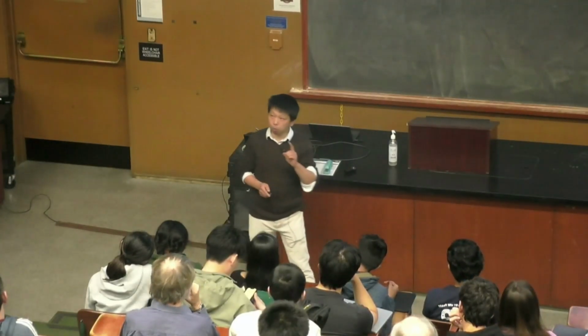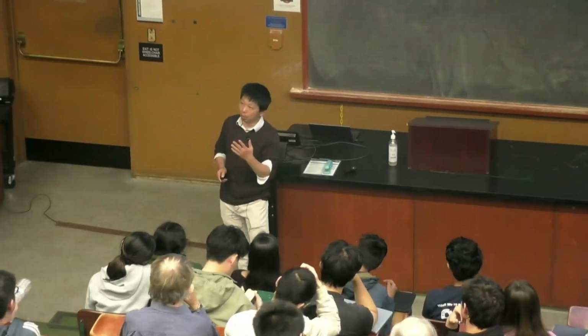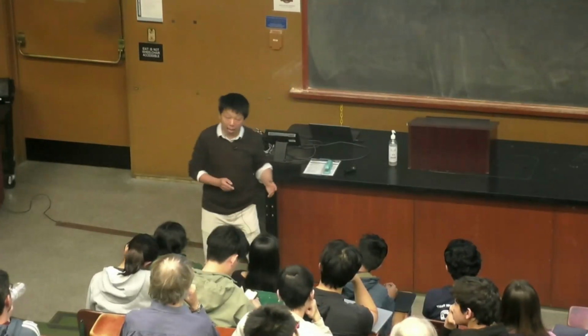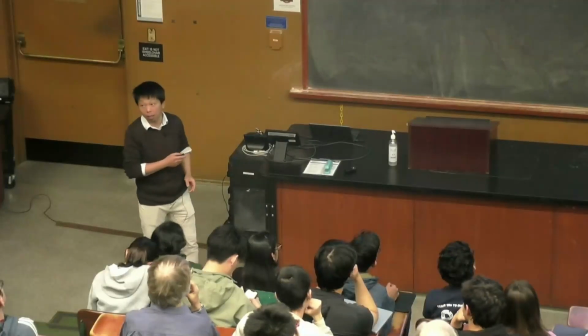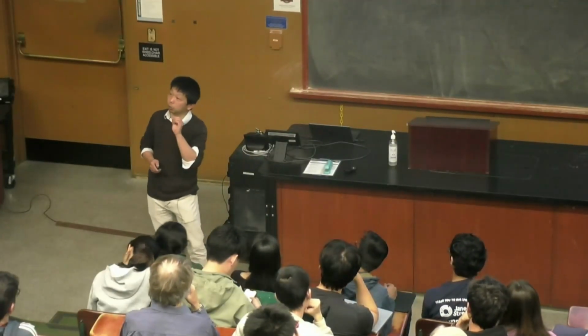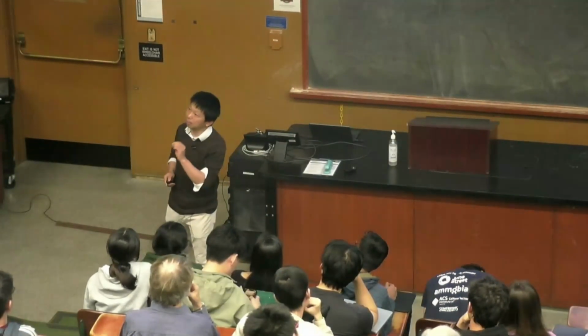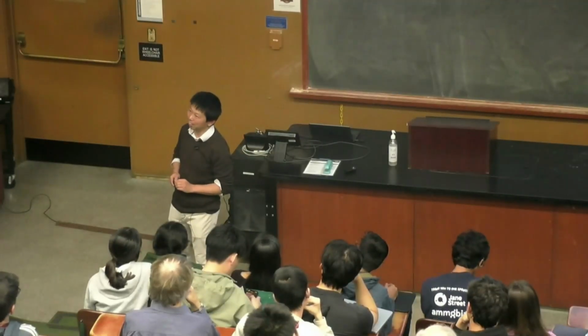Okay, so we change the magnetic field. We can measure either charge density or spin density. So these are all spin susceptibility. We are making use of circularly polarized light to directly determine the spin density in the system, not the charge density.